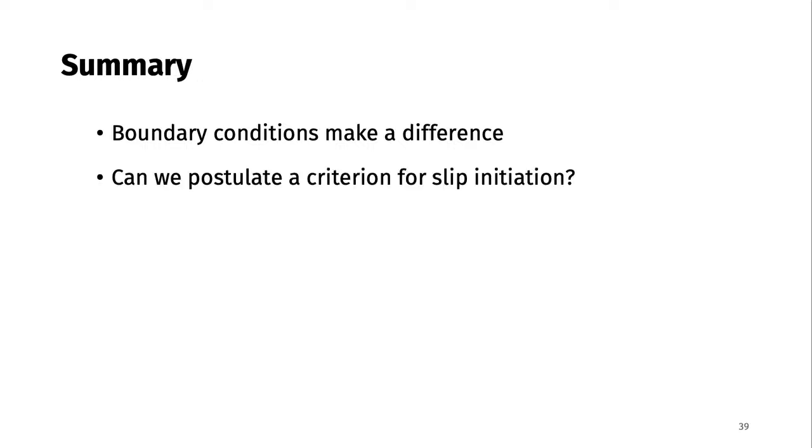Now this begs a question, can you postulate a criterion for slip initiation, right? Now, just like I said, the criterion for crack nucleation is a far tougher problem than the criterion for crack growth, right? If you have an incipient crack, you can say under what loading the crack will grow. But given a loading where there's no crack inside the material, predicting when a crack will form is not very easy to do. And so can you use something like this to give an analogous explanation for slip initiation, which is basically the same problem.